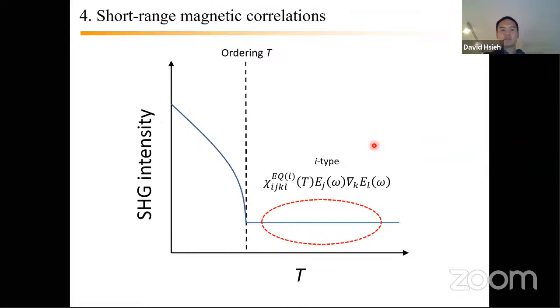And lastly, I've gone through a few ways in which magnetic ordering can lead to changes in SHG intensity. But one needs to be careful too. If you see upturns in SHG, that doesn't always mean that you're actually seeing long range magnetic ordering. In fact, we've done some recent experiments to show that even if you start developing magnetic correlations, that's enough to change your SHG intensity. And I want to just spend two slides going through this example.